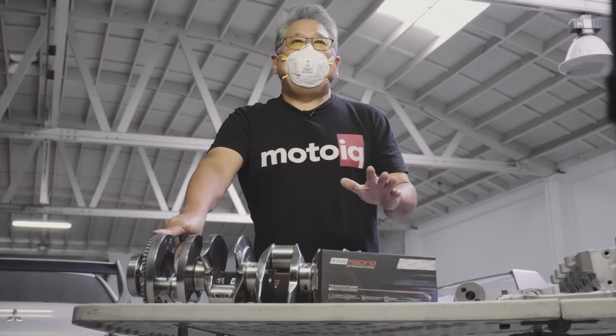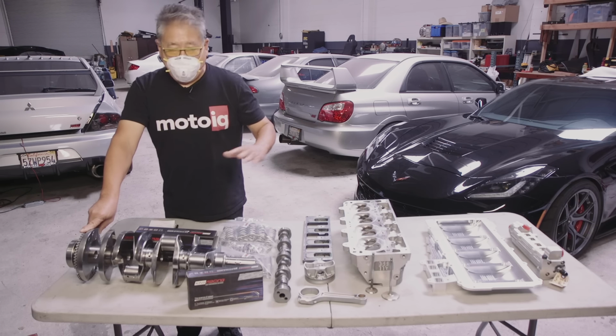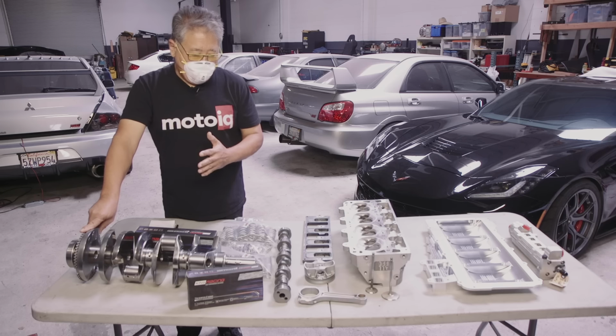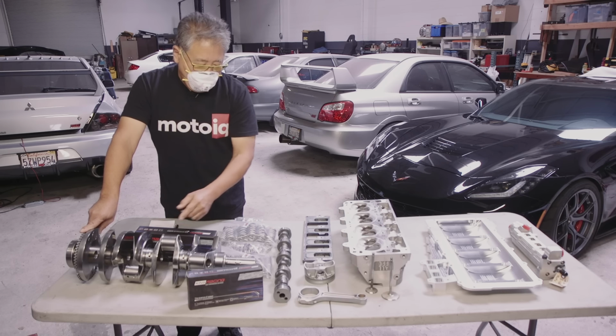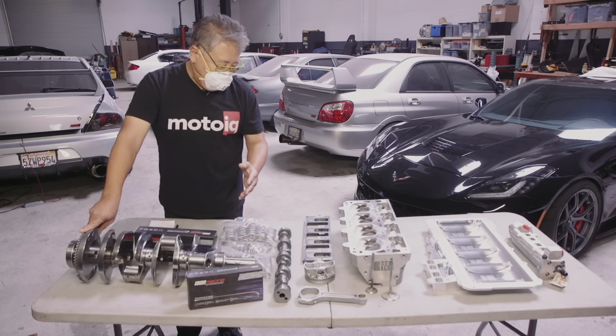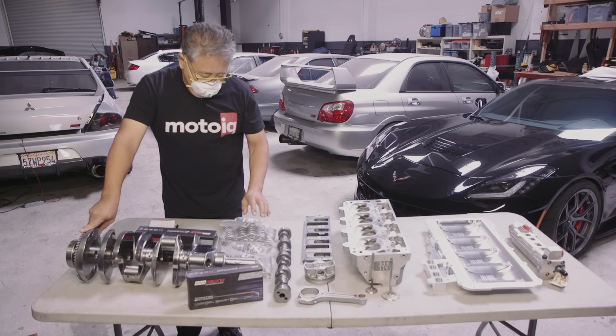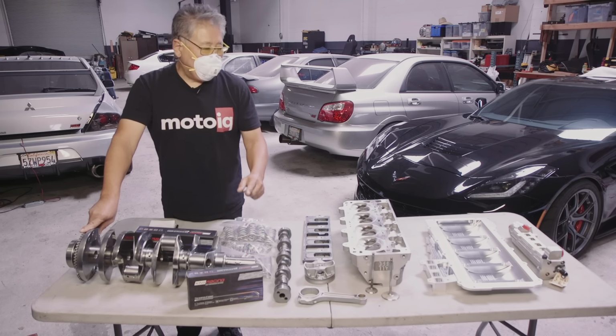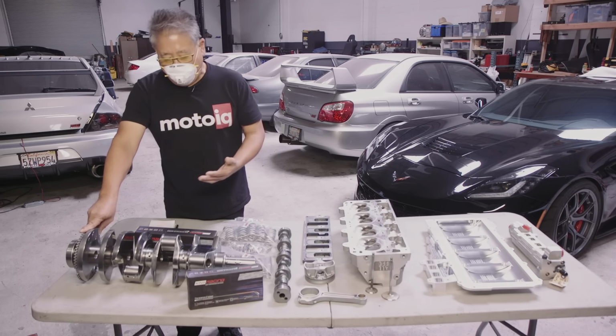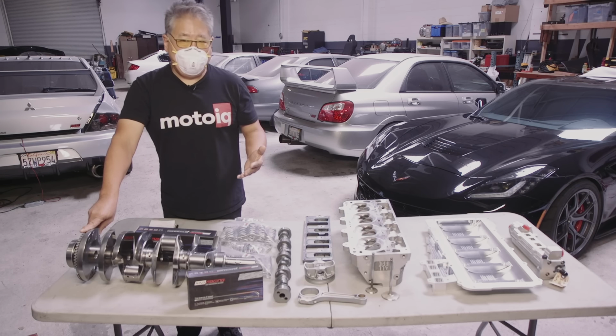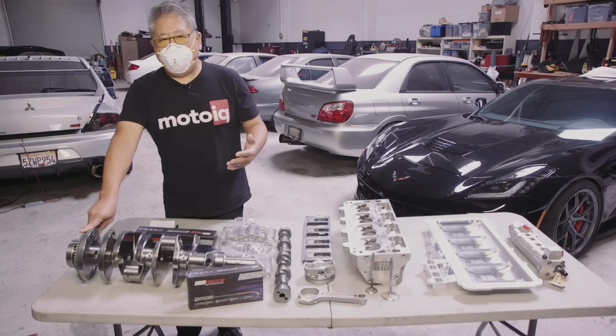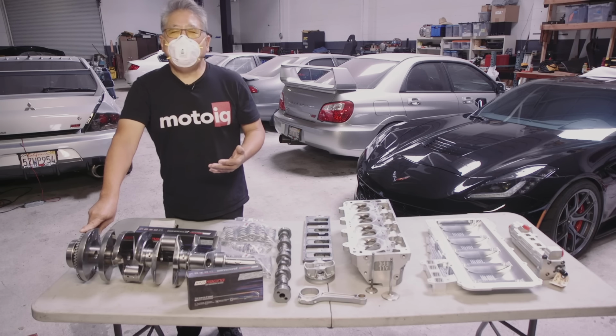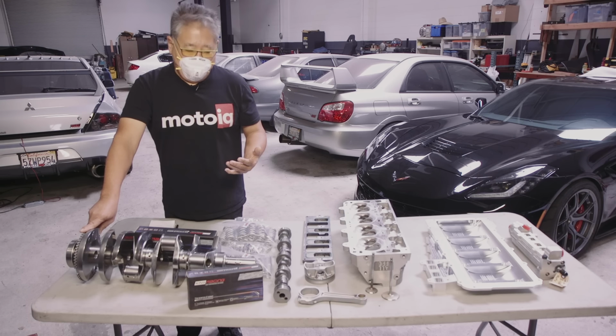And we WPC anything that can rub in an engine. On the block, we WPC the cylinder walls; we WPC the crank, pistons, rods, camshaft. We WPC the valve springs because that helps their fatigue strength. Anything that rotates or rubs on a really serious engine, we WPC. And we found that this actually helps life by maybe as much as 50%, sometimes 100%, depending on what the component is. Our valve springs don't fatigue nearly as fast.